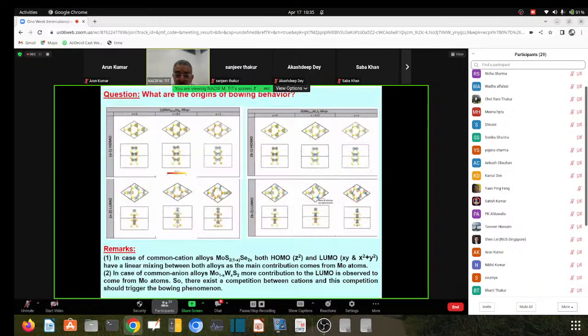So the coefficient of x squared here, in our theoretical is 0.32 in case of this parabola, and in the experimental 0.26. So we have good fitting, good closeness. Similarly for the linearity, it's minus 0.33 and minus 0.33, which means we are doing good in terms of fitting our data and comparing them to the behavior of experimental alloys.